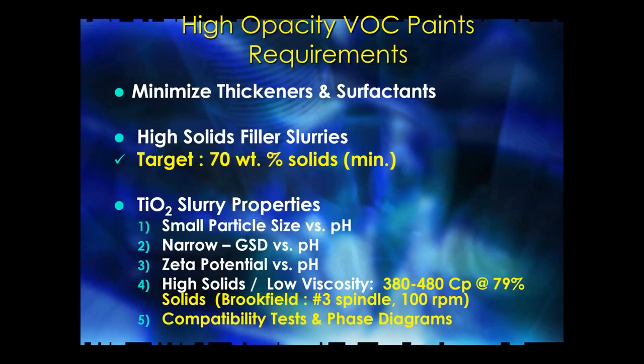So having had that as a tool, they also were able to use the Horiba to develop a fingerprint. They set it on the refractive index of the TiO2, and then they could see all the peaks of all the other particles they had, and they could tell whether a paint was good or not, and the formulation was followed by looking at the peaks and the intensity of the peak. So we've got three applications, and I'll tell you, this instrument paid for itself in 3 months.